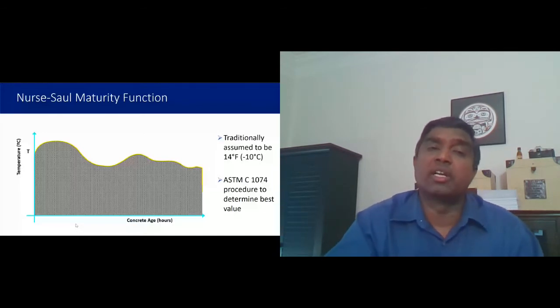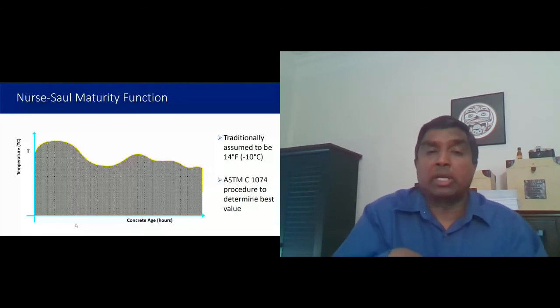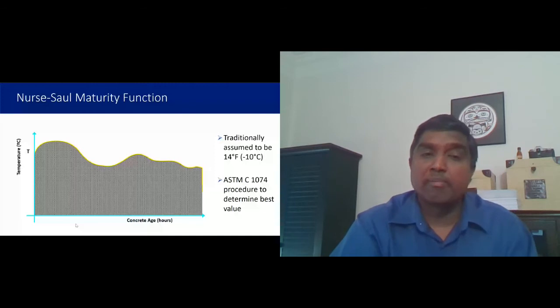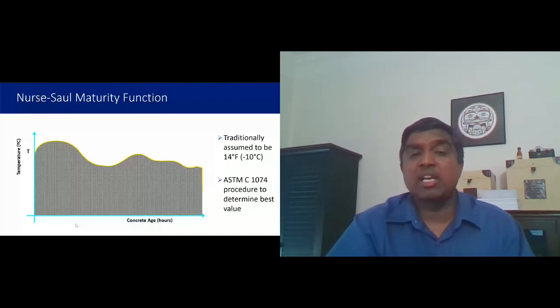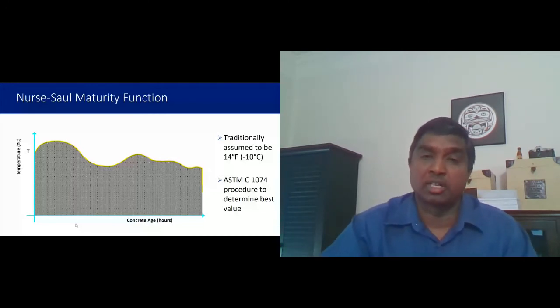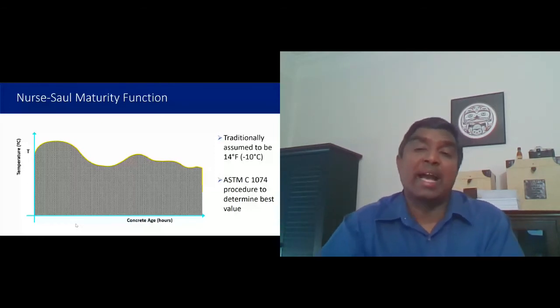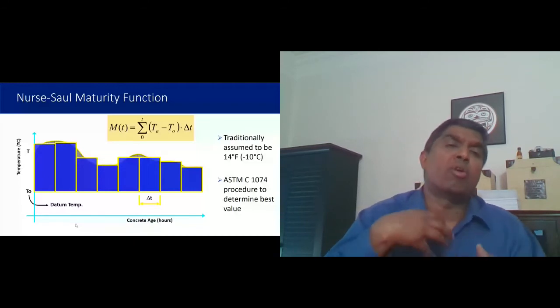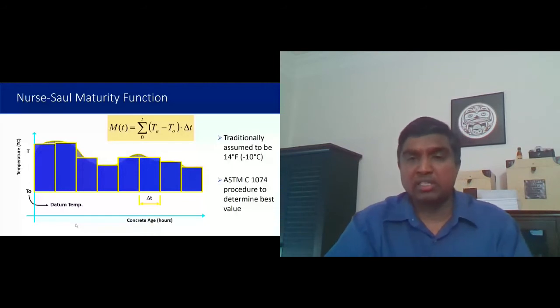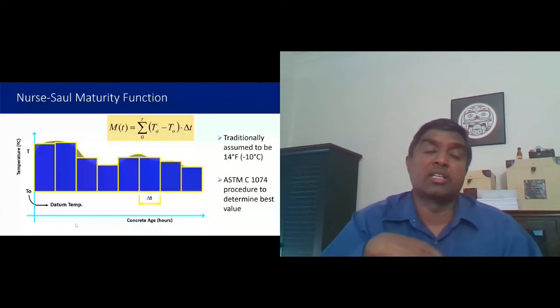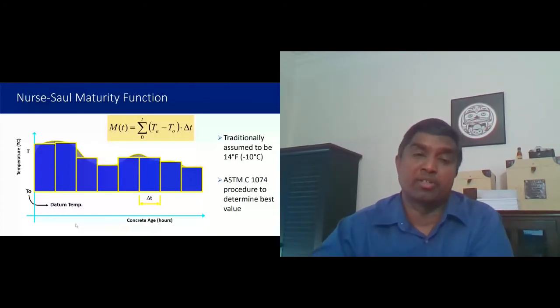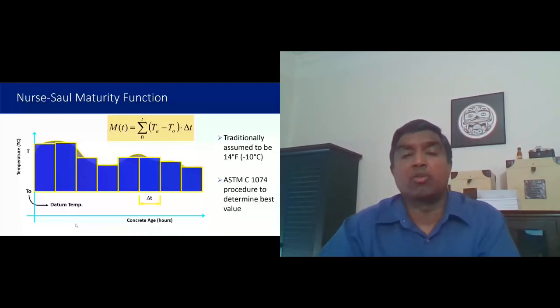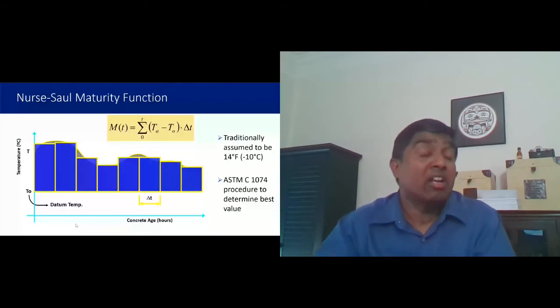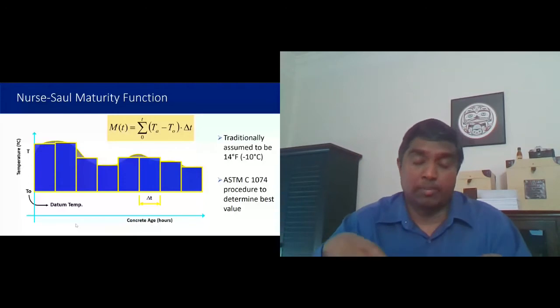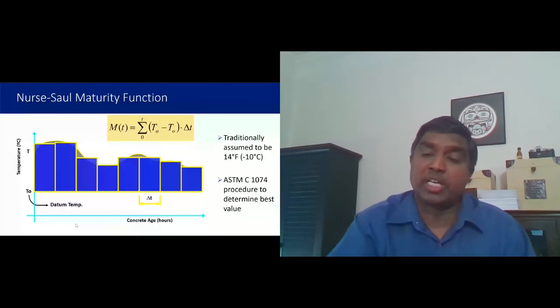So I did mention earlier on that we are following the Nurse-Saul maturity function. What the Nurse-Saul maturity function really does is it's a mathematical function to calculate the area under the curve. That's all it really is. Now, if you remember, I mentioned this temperature called datum temperature. So any temperature below the datum temperature, we just ignore it in our mathematical calculations. Okay. Now, traditionally, we assume that that number is minus 10 degrees Celsius or 14 degrees F. But if you want to be more accurate with what you're doing, within the ASTM test procedure there is a process that you can follow to obtain the accurate datum temperature. To be honest with you, with the work that we do with our concrete trailer, we rarely calculate the datum temperature. Most of the time, we just end up assuming a number. For paving applications, again, I'm just talking from my experience, assuming a number would be just fine.